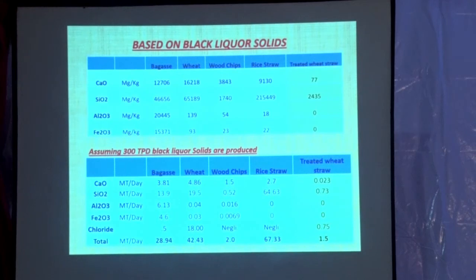And in this process, water, usually if you see the wet washing water, if we are operating wet washing of 500 TPD wheat straw, approximately 80 M3 per hour water is going to the ETP. In our system, because we are using Na2CO3 and H2SO4 for neutralization, water definitely has some COD as well as chemical also. But in our system, water going to the ETP will be 0. There won't go any water to the ETP. This water will be regenerated and it will be reused. And all the salts will be removed separately.